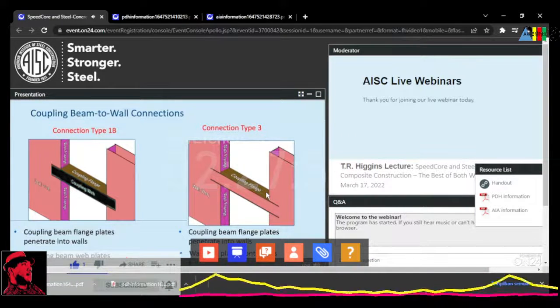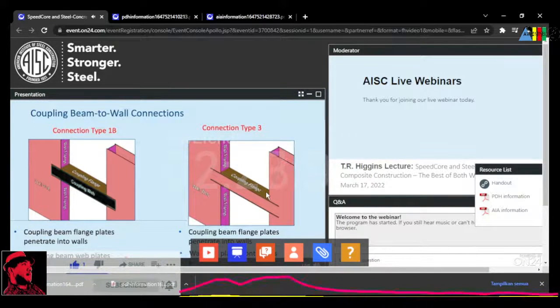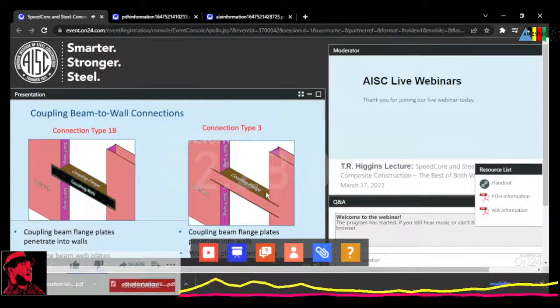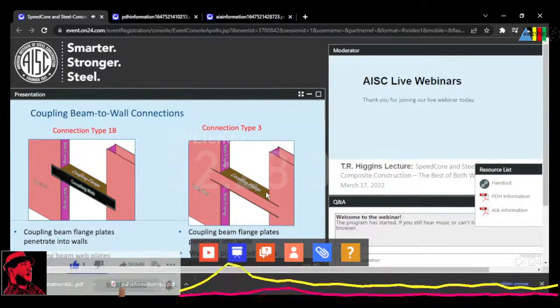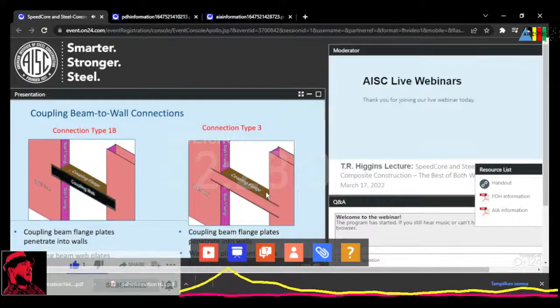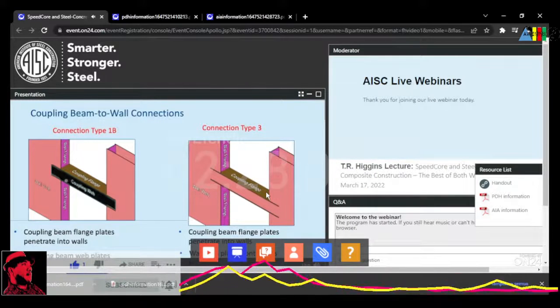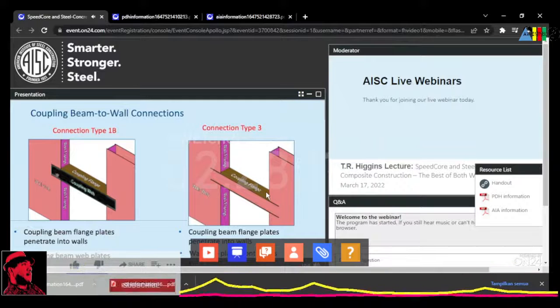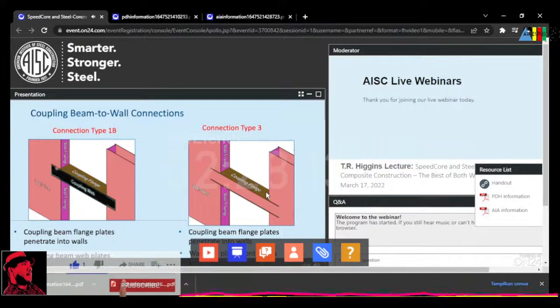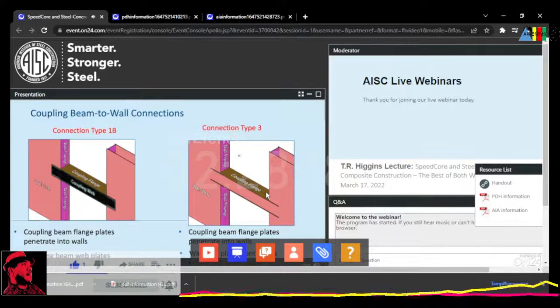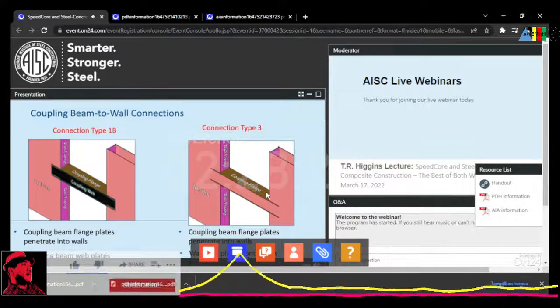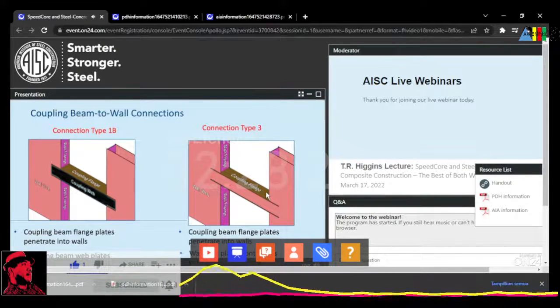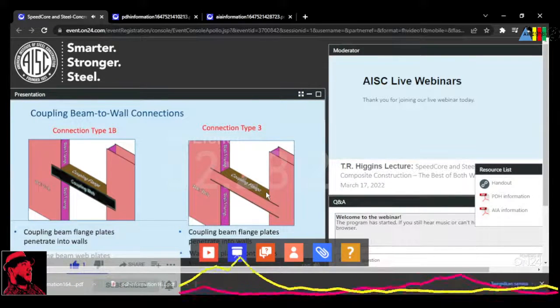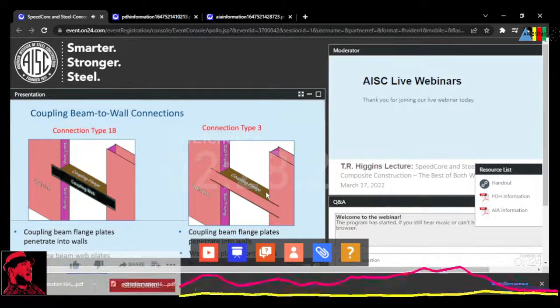2 of these connection types are shown schematically here. On the left is connection type 1B, where the coupling beam flange plates penetrate into the walls and the coupling beam web plates are lapped and welded from the outside to the composite walls. Another connection type 3, shown on the right, has continuous web plates between the composite wall and the coupling beam, whereas the coupling beam flanges penetrate into the walls and are welded.